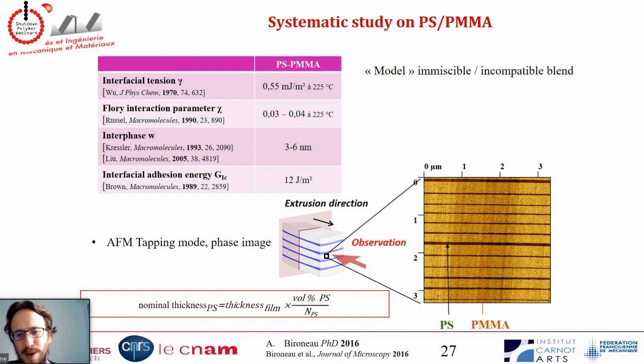So what we did is a systematic study of one system. We chose polystyrene and polymethyl methacrylate. Why did we choose this system? It's because it's some kind of a model of immiscible and incompatible blend. This blend has been studied for the last, I don't know, 40 years, and many interfacial parameters have been measured and can be found in the literature. So we studied only this system, but we checked systematically all the processing parameters. So we changed the thickness of the film, the ratio of the two polymers, the number of multiplying elements, and we then characterized the structure of our films.